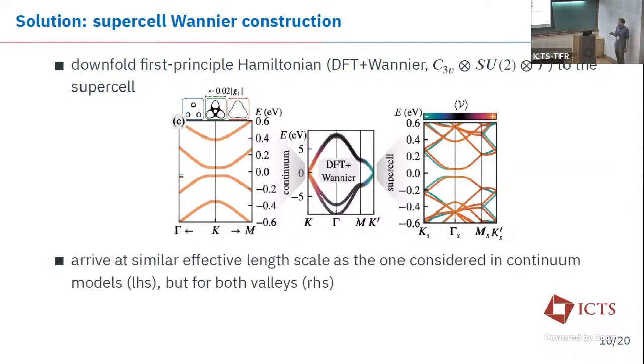The interesting thing to note is that we can arrive at a similar length scale as the one considered in the continuum model by just taking a large enough supercell. For all plots shown in this talk, I will go to a 24 by 24 primitive cell supercell, and this is enough to resolve the length scales that are significant in the continuum model you see on the left. As I said, we have both valleys in the supercell model, both backfolded to the gamma point, whereas in the continuum model, we stay at the K point, and we have to truncate momentum space, with one valley per truncation, so to say.